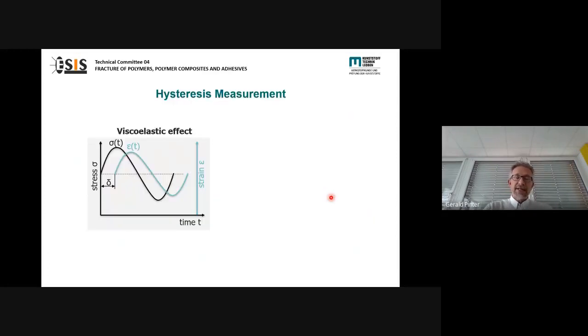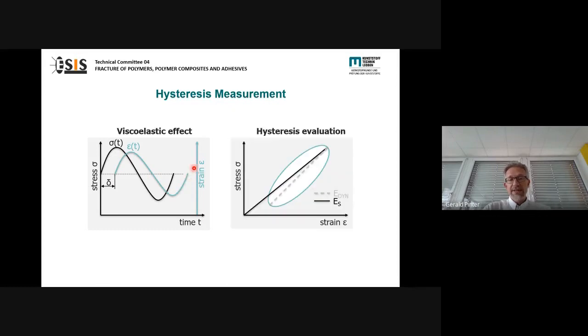If you want to get more information out of the test, and not only the cycle numbers to failure at different stress levels, you have to measure the hysteresis. So you have to measure the strain during the test. So this is again the stress. How the specimen test is controlled, and you measure the strains. And if you plot then stress over strain, you typically get the hysteresis at the defined cycle numbers.